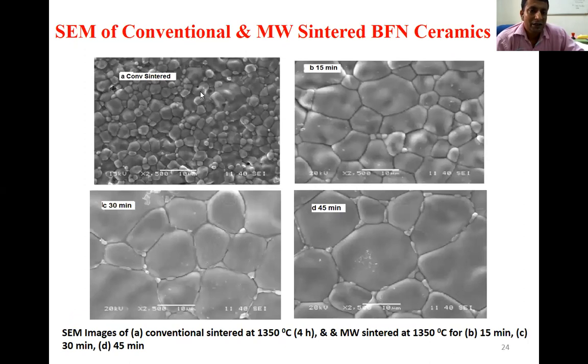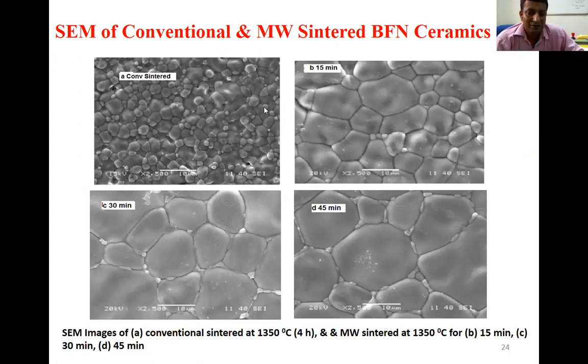SEM micrographs. Here, this one is the conventional sintered BFN system micrograph, and this one is the microwave sintered, and we can see that they are very dense. So the very dense microstructure is there, and of course we'll be seeing the electrical properties also. So here, at 1350 degrees Celsius, the time duration was 4 hours, and here 15, 30 and 45 minutes, and we are getting very compact, very dense microstructures.